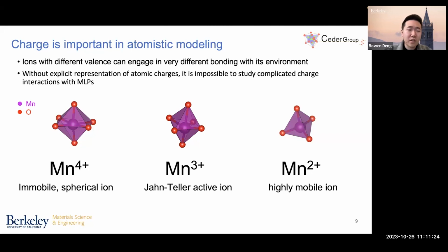For example, in ionic systems, the high-valent manganese 4+ ions are often considered as immobile spherical ions that only ever reside in the octahedral coordination by oxygen atoms. Manganese 3+ is a Jahn-Teller active ion that tends to radically distort its local environment, leading to an anisotropically distorted octahedral framework. Manganese 2+ is a highly mobile ion that tends to sit in a tetrahedral coordination with oxygen ions. And we often consider them as highly mobile, so they really want to diffuse within the system. However, without the explicit representation of these atomic charges, it is really impossible for us to study these complicated charge interactions like the manganese case.